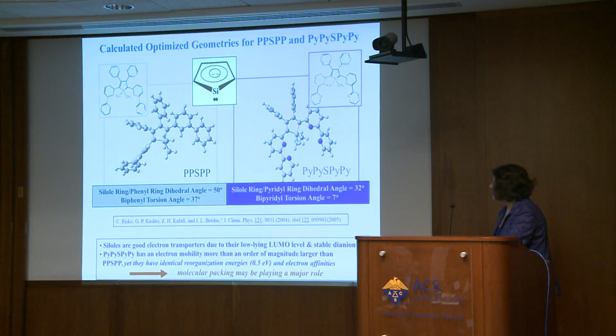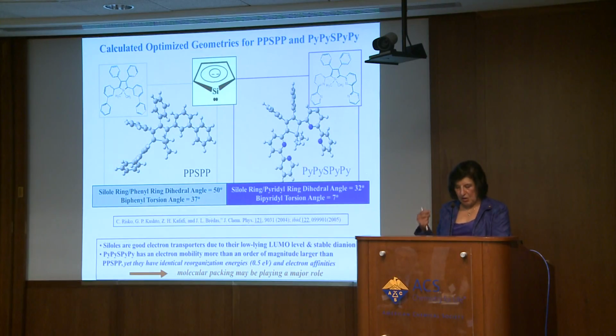We also collaborated with the group of Jean-Louis Brédas to do some calculations to understand why these materials, with a very small change, behave differently. These are very identical compounds except for this element. We changed carbon for nitrogen here, essentially. And we wanted to understand why one is a very good electron transporter and the other one is not, because both molecules have identical electron affinities and the same reorganization energies. And reorganization energy is a measure of the charge carrier mobilities.